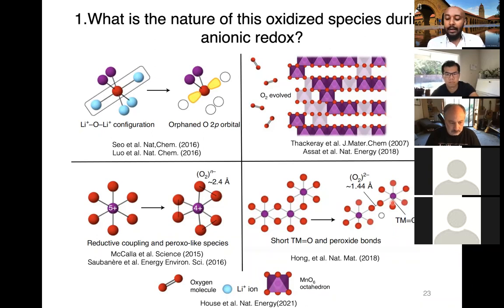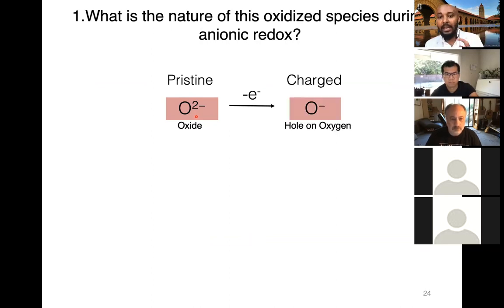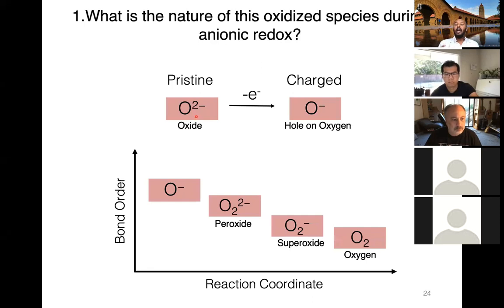And to be able to answer this question, first we have to understand the chemistry behind whenever we have anionic redox. So in the pristine material, we have the material in oxide state, that is O2 minus. When we do anionic redox, when we charge, what happens is we remove electrons from the material. Therefore, we have O minus, or as a physicist likes to call it, holes on oxygen. However, the O minus is not stable. Therefore, the O minus would like to form a dimer oxygen-oxygen bond as a form of peroxide, superoxide, or oxygen. So this is the fundamental chemistry of what happens when we perform anionic redox in these oxide systems.